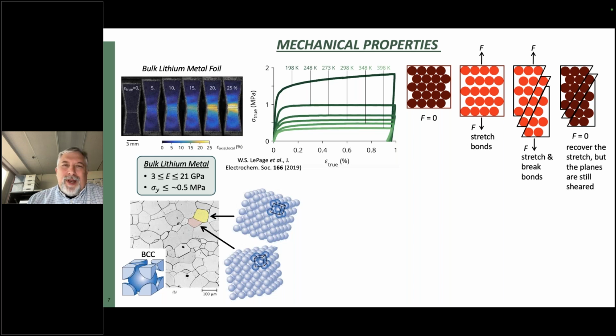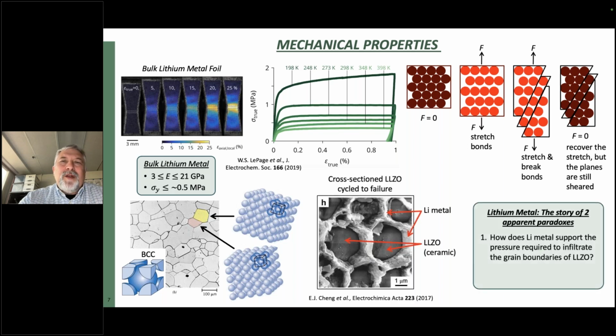So now let's take a look at this micrograph in the bottom here. So here we're looking at a cross-section of a separator that's been cycled to failure. And as you can see, the lithium metal has penetrated all along the grain boundaries of this ceramic separator here, right? And so this is really puzzling because the stress strain curve up here says that bulk lithium metal is basically soft as butter. So it's not clear at all how lithium metal can support the pressure that's required to propagate along these grain boundaries of a ceramic separator, yeah?